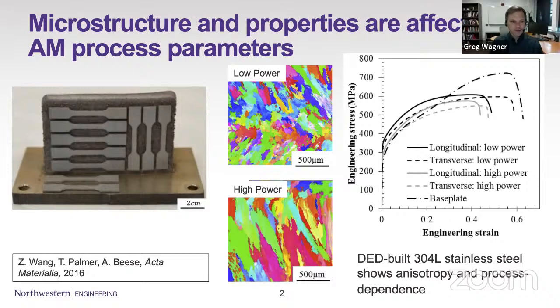So here's some work that I like to highlight from the Penn State group, where for a directed energy deposition experiment, they ran the same build with both low and high power, and saw an obvious difference in the microstructure that results, right? So smaller grains for the low power case. And there's a resulting difference in the material properties too, right? Where with the smaller grains, you might expect the low power case ends up being a little bit higher failure stress or higher failure strength. And there's also an obvious anisotropy because of the anisotropy of the build and the resulting structure.